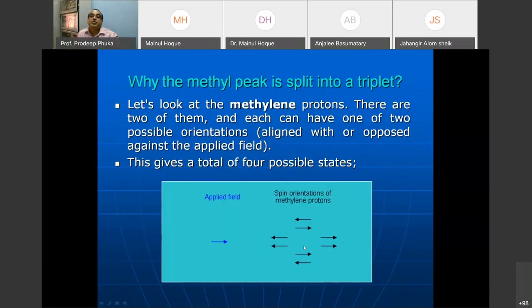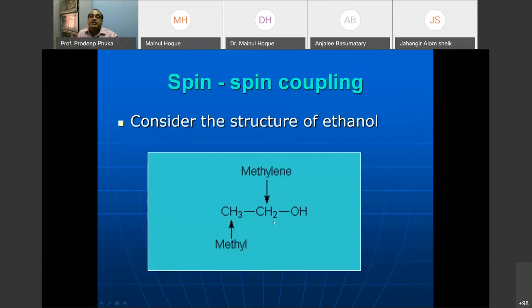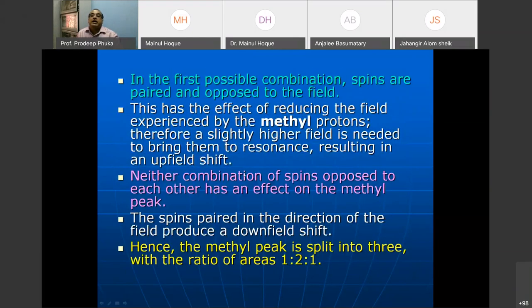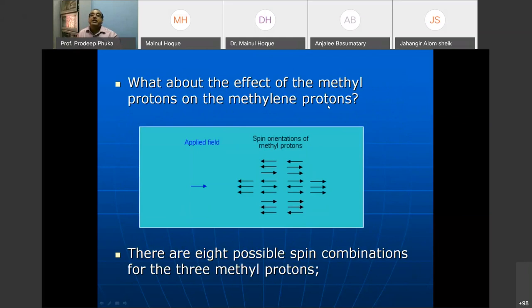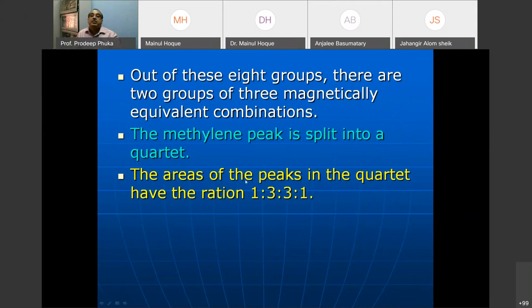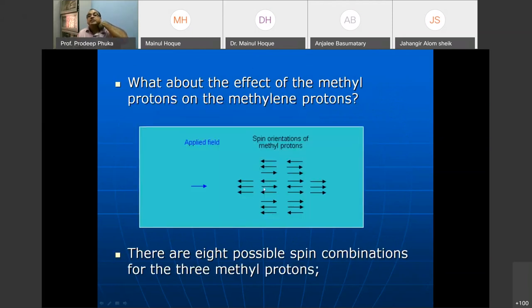Which methyl peak? You can see here, this methyl peak is affected by these two particular protons. And in the same way, these two protons are affected by three protons. And you see here, this is a methyl peak. So one orientation, three orientations, three orientations, one orientation. So there are a total of eight possible spin combinations, and it will split into 1:3:3:1. So why 3:3:1? Now you could understand that there are three orientations that have the same energy.